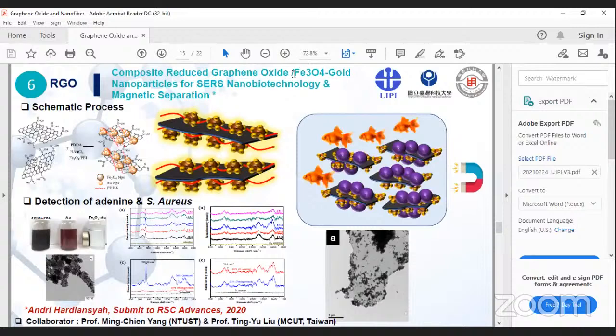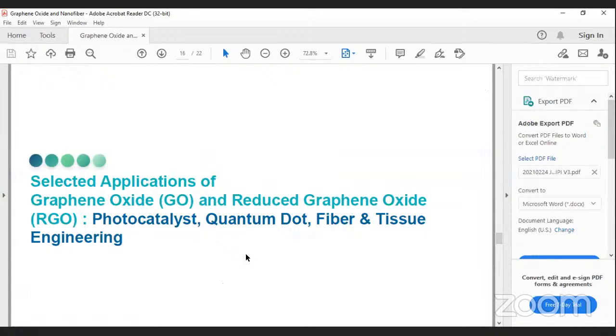We try to put iron oxide in the graphene oxide together with the gold nanoparticles, and we can get magnetic properties and also SERS properties by using this kind of nanocomposite. And here are some TEM images of the nanocomposite. And then probably the last applications where we might use graphene oxide and their derivatives are photocatalysts, and then quantum dot fiber and tissue engineering based on graphene oxide.